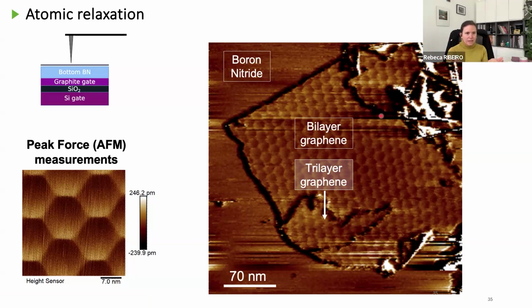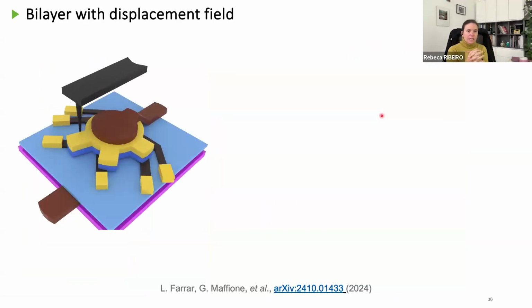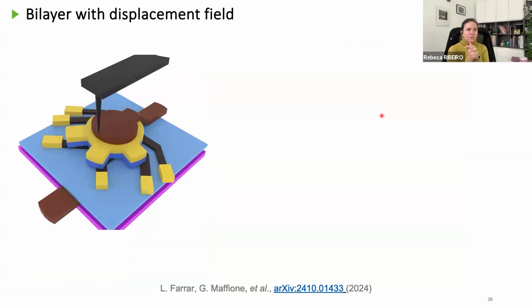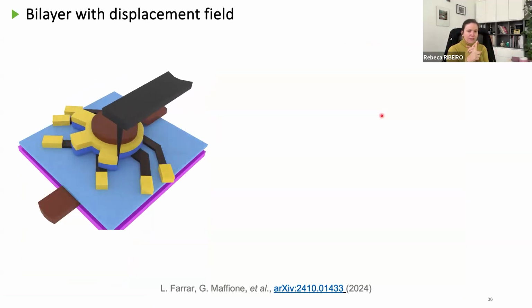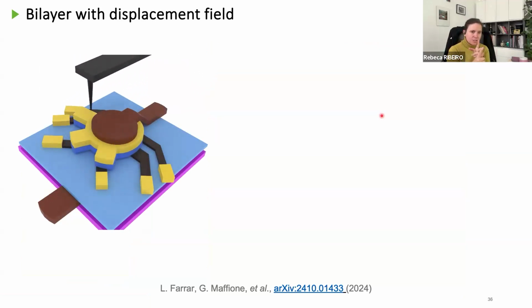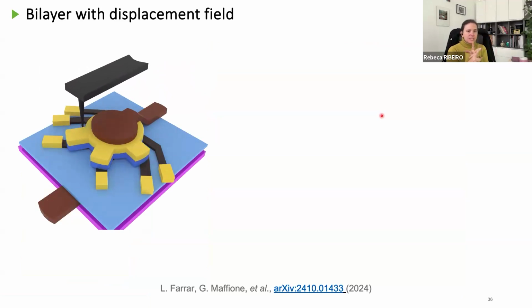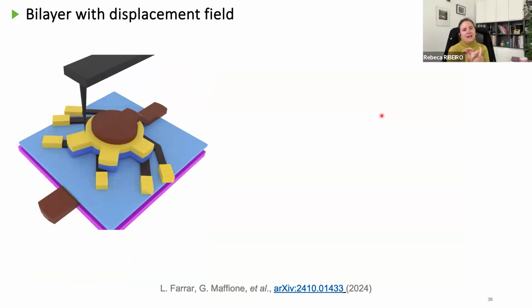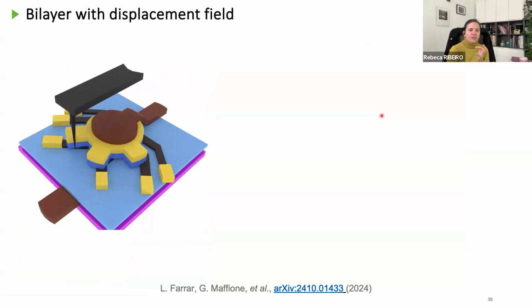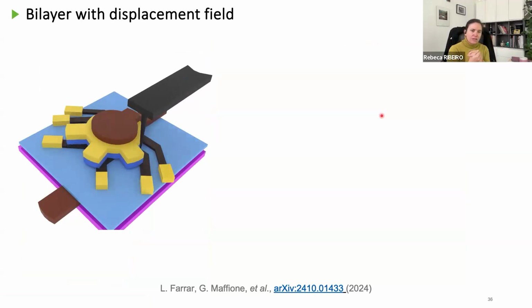This is most likely related to the atomic configuration of this. So we wanted to go one step further with this technique, and we developed a new sample architecture that in fact allows us to change the crystallographic angle, measure the transport properties in situ, and have an electric field that is perpendicular to the system.